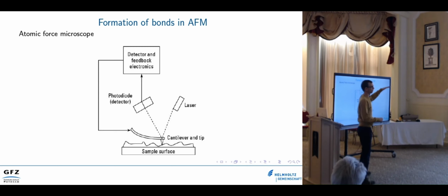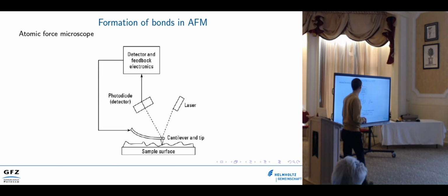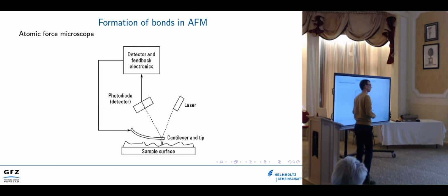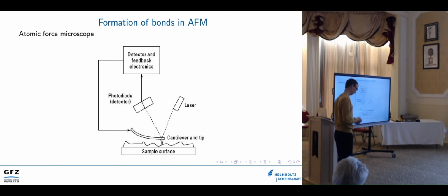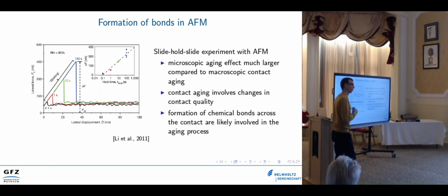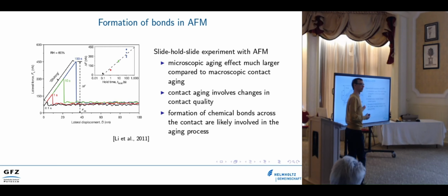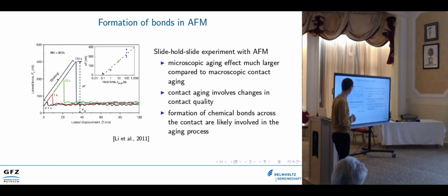So an experiment that illustrates that really nicely is the atomic force microscope experiment here, where we have this cantilever that is placed on the surface at an atomically close distance, as I mentioned before. And then it is pulled across the sample, and the force and the deformation are measured. So now we see a dependency on the force that is needed to pull the atomically small needle away. That depends actually on the time that this needle has been at rest at that particular location.